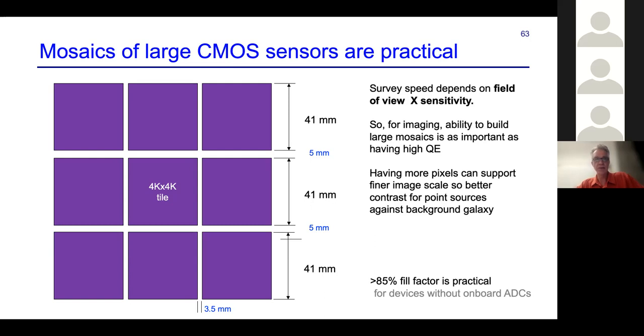And I remind you of the obvious fact that if you're doing an imaging survey, sensitivity is not the only factor. You want to have area. It's just as valuable because it means that you don't need as many images to cover a given area. So we get a boost in sensitivity in CMOS, both from the fact that the QE is higher and the fact that we can afford to build very large focal planes quite practically. The gaps that I show here are realistic kinds of gaps for the sort of packaging that we might envisage. This particular image that I'm showing here has an 87% fill factor. And so that's perfectly reasonable.